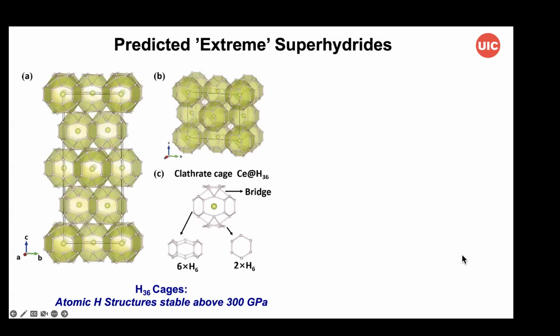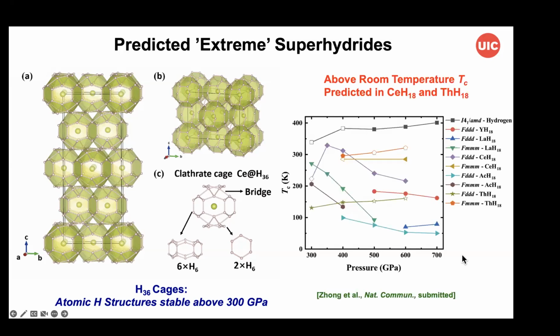So we have a fairly good understanding for the binary systems, and until recently we thought that we basically had the maximum stoichiometry in the binary systems that produce this high TC, at least over the range of pressures that can be reached experimentally, so 300, maybe 400 GPa. But in some recent work that was conducted by the Jilin University group that I was a part of, and this work was just published in JACS, we found yet higher TC and higher hydrides that we're calling extreme superhydrides in the binary system. And these have 36 atom cages, still higher hydrogen content. And for some of them, the cerium and the thorium, above 300 GPa, TCs that are predicted using the same sort of conventional approach that's been used so successfully for the other systems, TCs above room temperature. It was actually published in JACS just last week.